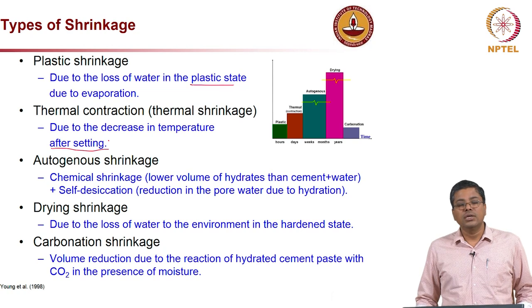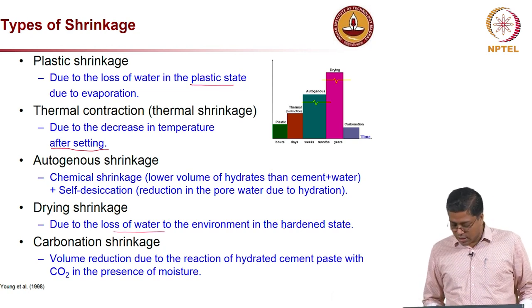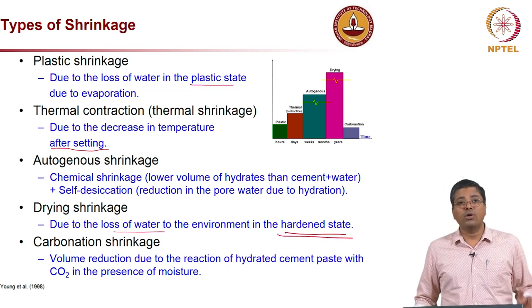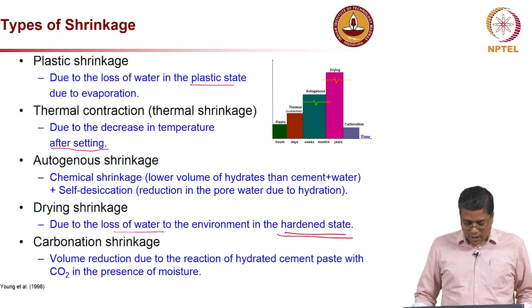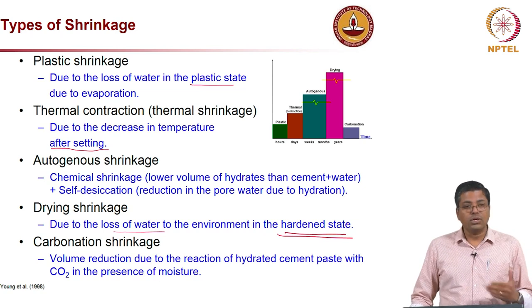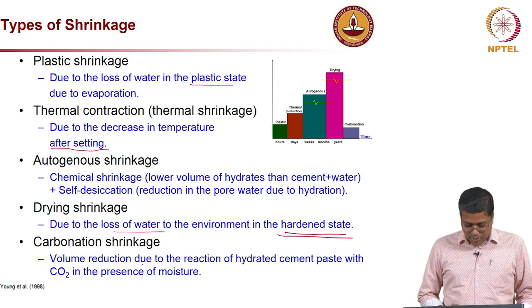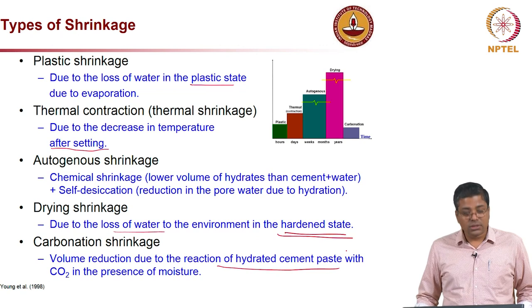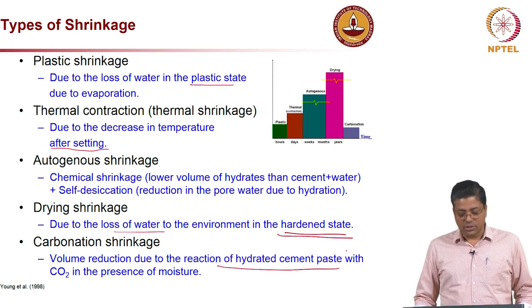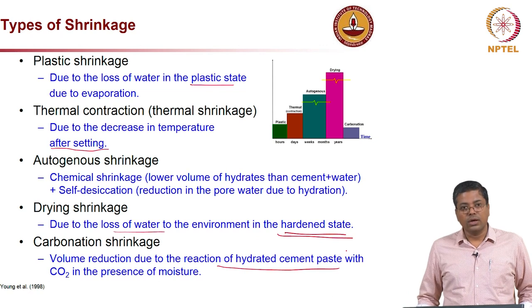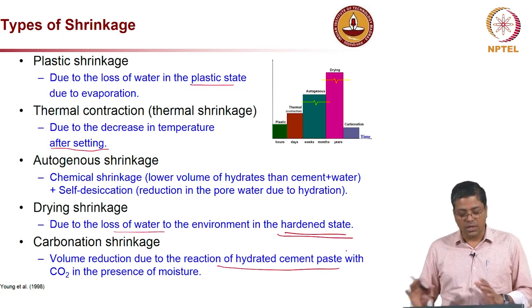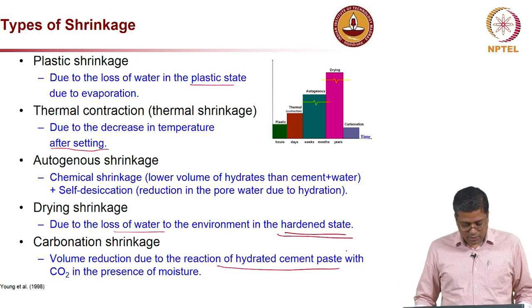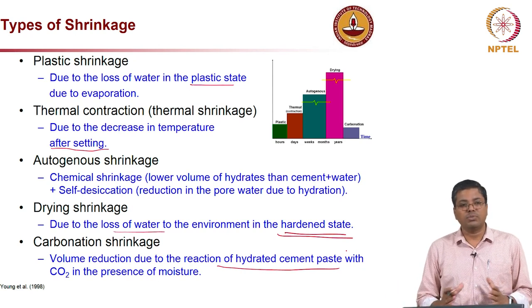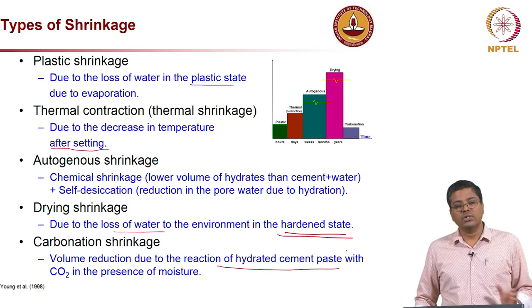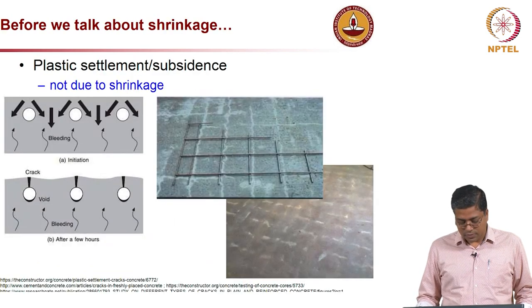And drying shrinkage is mainly due to the loss of water after the concrete has already hardened, basically due to the drying of the hardened concrete. And carbonation shrinkage is mainly because of the reaction of the cement paste with the carbon dioxide in the presence of moisture, which leads to calcium carbonate, which gets precipitated in the space available within the concrete, and even free space available within the concrete, which eventually leads to shrinkage.